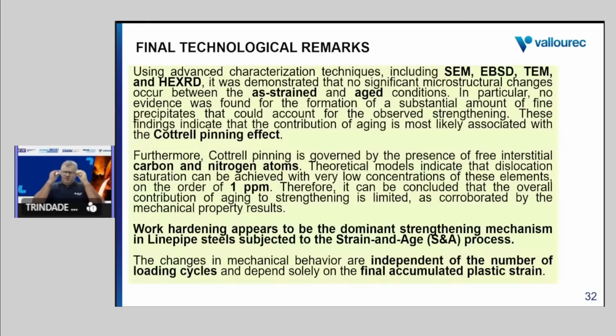So now I come to the conclusion, my final slide. We used advanced characterization techniques including SEM, EBSD, TEM, and high energy X-ray. It was demonstrated that no significant microstructural change occurred between the as-strained and aged conditions. In particular, no evidence was found for the formation of a substantial amount of fine precipitates that could account for the observed strengthening. This finding indicates that the contribution of aging is most likely associated with the Cottrell pinning effect. Furthermore, this is governed by the presence of free interstitial carbon and nitrogen atoms.